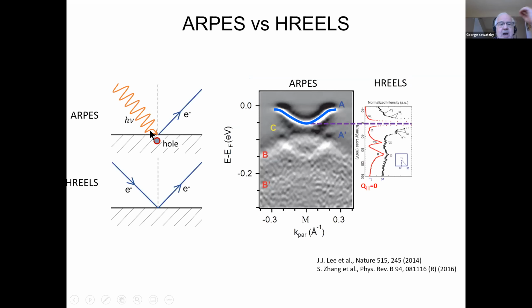In photoemission, you have an electron coming out. Now, the reason why this is interesting is because there are high-resolution electron energy loss experiments done where you shoot an electron in on the same system, and scatter it more or less specularly, and look at what the energy loss is. And that energy loss spectrum is shown on the right-hand side under the HREELS, okay?